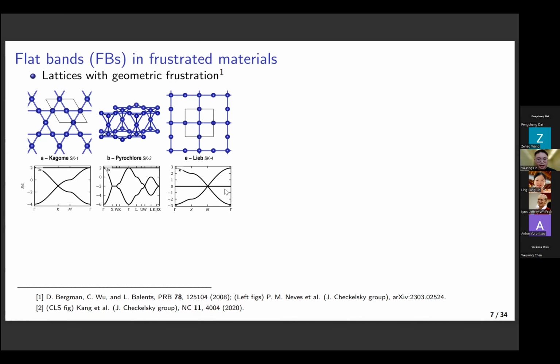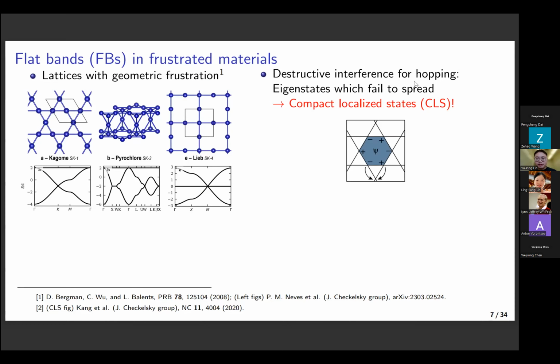So what is the reason why these lattices have the flat band? This can be understood easily from the destructive interference of hopping. Let us take the kagome lattice as an example. If we put a wave function with opposite signs at the two sites here, and we look at the hopping onto the third site here, then we'll see that because the two sites have opposite signs in the wave function, their hopping to this site will cancel with each other, so that the third site will remain at zero density after the hopping. And if we put the opposite sign wave function around a single hexagon, we'll see that even under the hopping of a Hamiltonian, the wave function will not spread and it will remain invariant under the hopping. So the wave function will be an eigenstate of the Hamiltonian, and we call it the compact localized state. These compact localized states are the elements of the flat band.